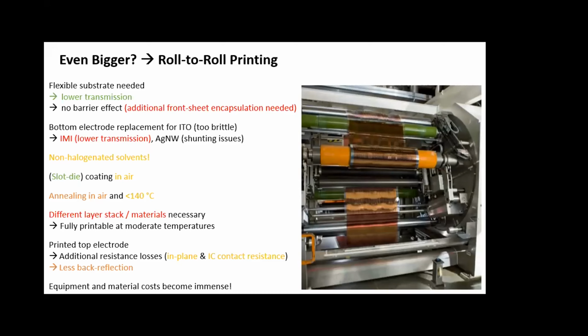Slot die coating is not that much of a problem if you have done doctor blading before, but the coating in air may be a problem. Annealing in air is definitely a problem. Working at lower temperatures due to the plastic substrate may be a problem because you cannot anneal at 200 degrees or whatever. A very big problem is the materials you use and the layer stack, especially the HTL nowadays.